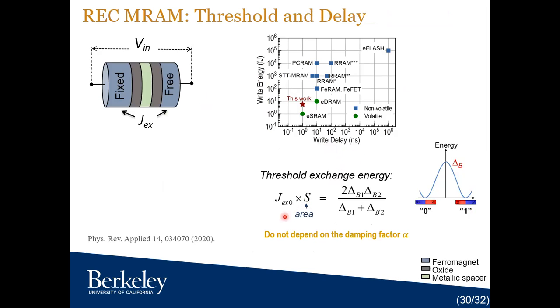Okay, another interesting thing is that now we also have a switching threshold, but now the threshold energy belongs to that exchange coupling energy. And the coupling energy depends on the anisotropy energy barrier of both of the magnets, but does not depend on the damping factor as I have shown for the spin transfer torque case. So this is interesting because the delay is still inversely proportional to the damping factor. So we can independently tune both threshold and delay, where for the STT we have a trade-off.